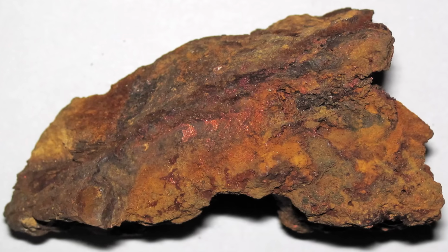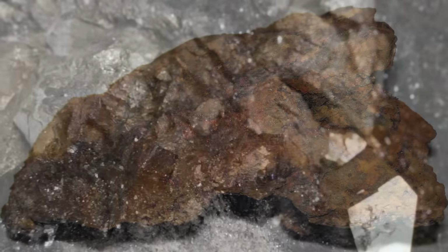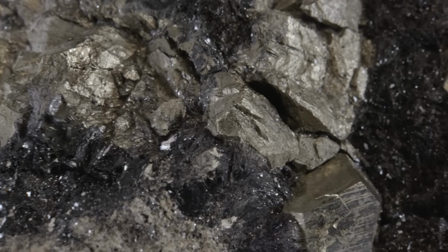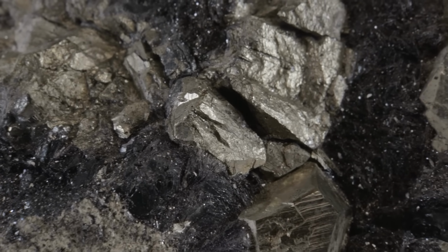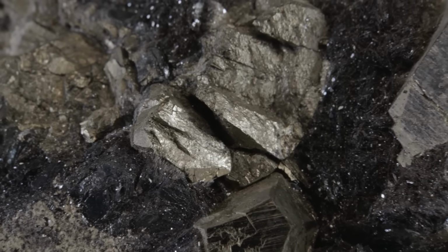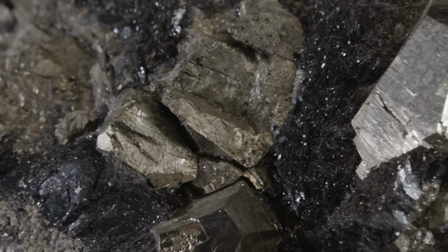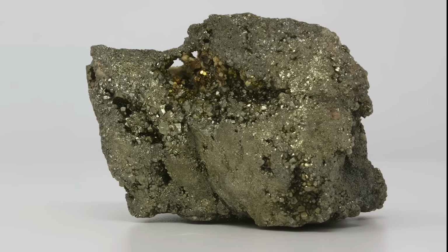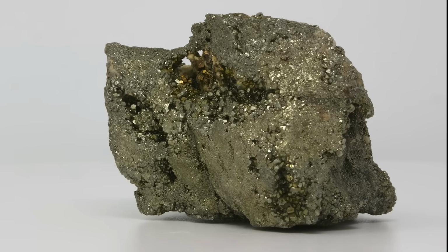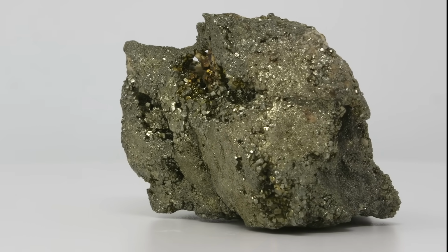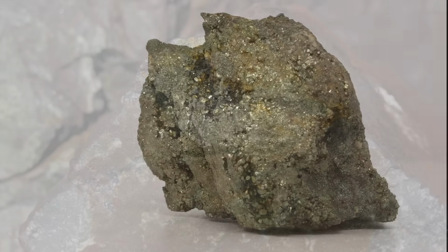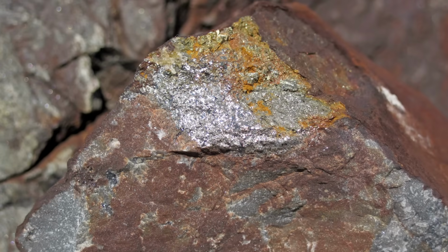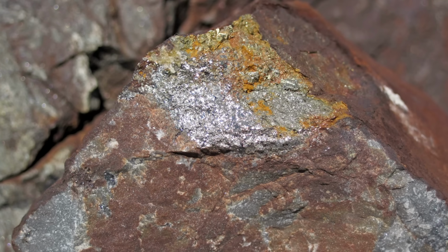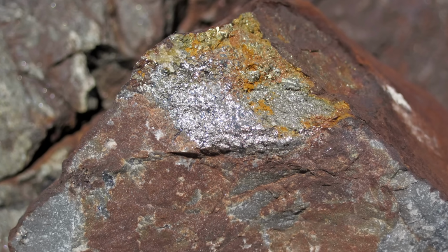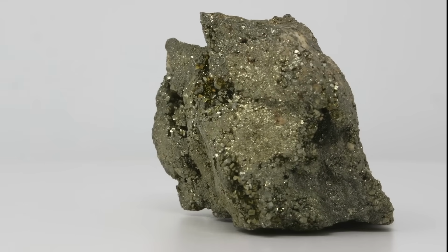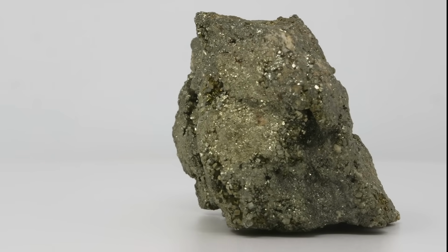What you're really looking at when you see strong iron staining isn't just iron. In many cases, you're looking at the ghost of sulfides. Minerals like pyrite and arsenopyrite, which originally formed deep underground in hydrothermal systems, carrying trace to significant amounts of gold within their crystal structures. In many cases, the gold isn't sitting freely in quartz. It's locked inside these sulfides at a microscopic level. Fresh unoxidized ore can look completely barren. You can crush it, pan it, stare at it under magnification, and still see nothing, because the gold is literally imprisoned inside the mineral lattice.